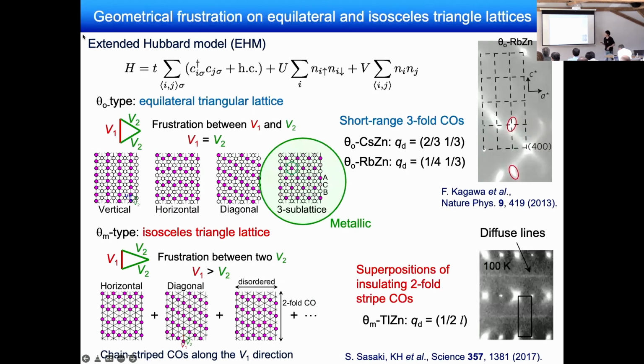Okay, so actually there are many theoretical calculations for the theta-type BEDT-TTF compound, which have been done by an extended Hubbard model like this. And here I will show the charge ordering pattern in the classical limit, where the transfer integral t is equal to 0. In the case of V1 equal V2, the ground state includes various charge ordering patterns like this: vertical, horizontal, diagonal, and three-sublattice charge ordered states. And this three-sublattice state is very metallic. And I think the orthorhombic system can be categorized in this region.